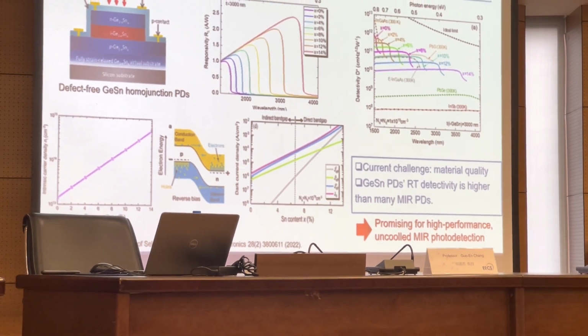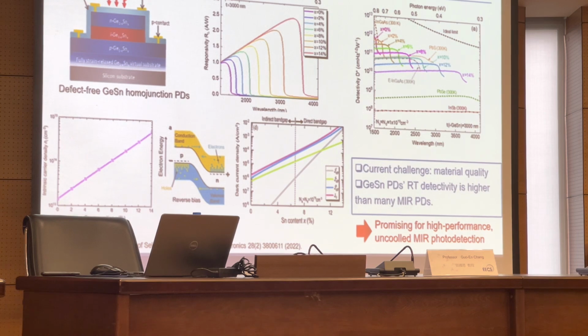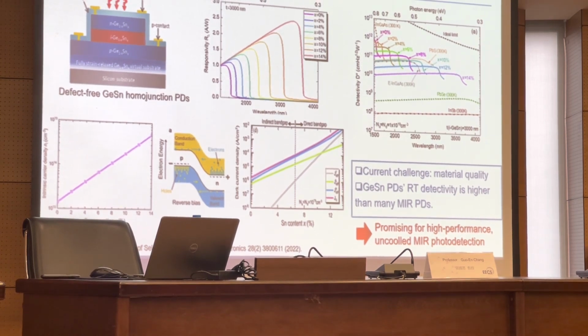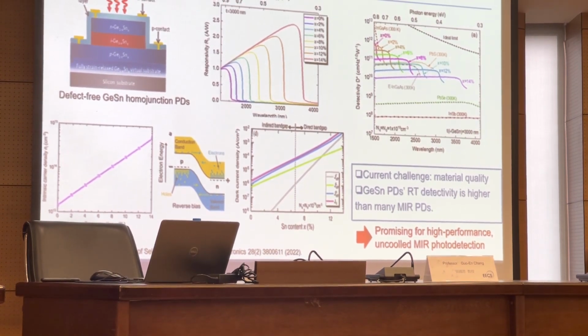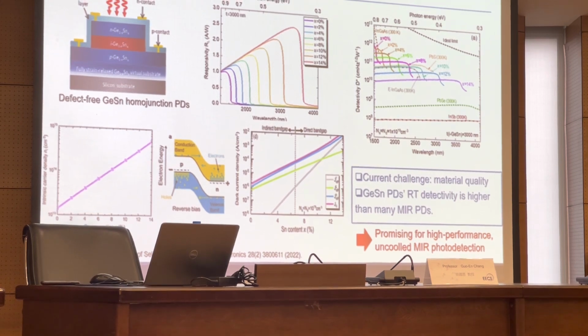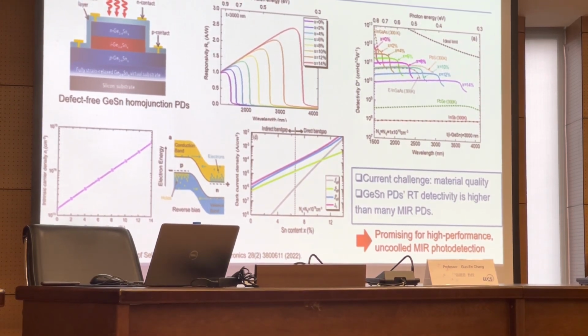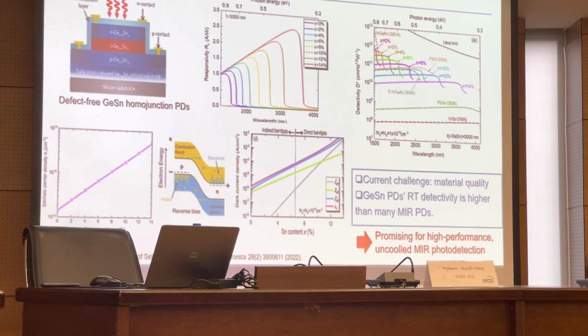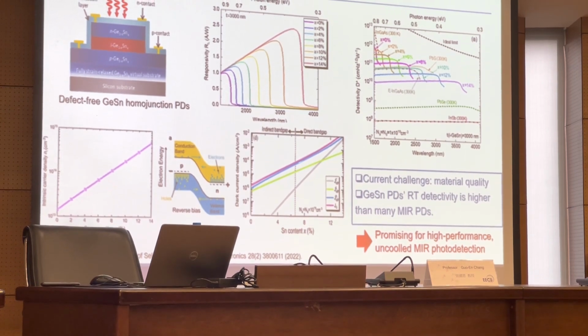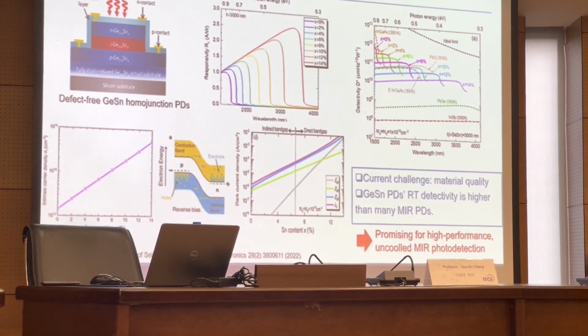After that, we calculate the diffusion dark current density. We can see the diffusion dark current density has different contributors from holes and electrons, but the total dark current density will increase when we increase the tin content.